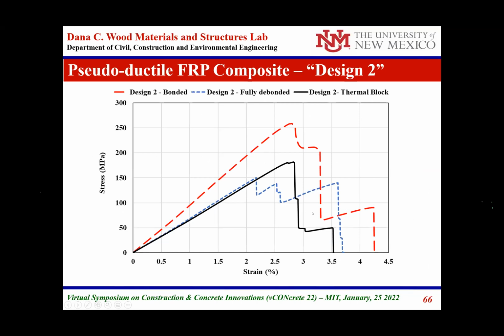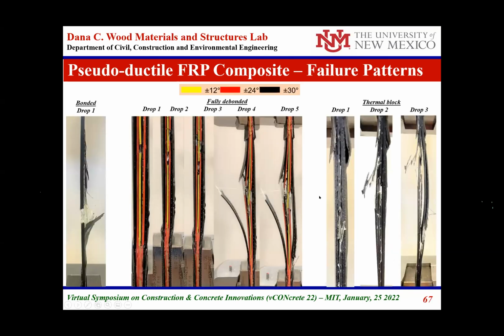This is for the case of the bonded, this is for the case of the thermal block, and this is fully debonded. So we can get 200 megapascal glass fiber, and it is a high ductility material with pseudo ductility and progressive failure. We're doing more work on this, looking at the debonding and failure patterns to learn how we can change the thermal blocks or thermal debonding during the printing process to produce a ductile composite.